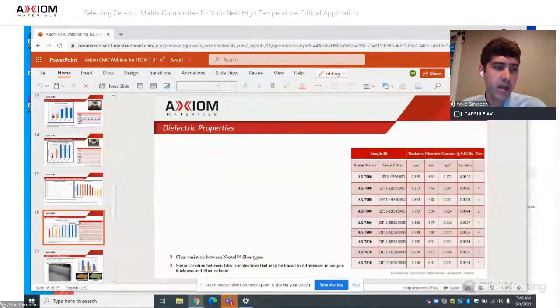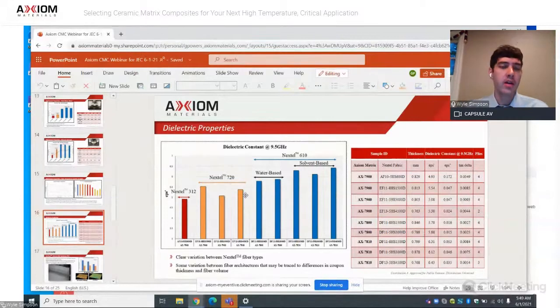Another interesting difference between the CMC components is the dielectric properties. The 312 fiber, which is the low-cost one, actually has a very low dielectric constant, and for that reason, it's typically used in radome applications, where you want to send a signal through without losing too much of it at high temperatures. So here's the difference: 610, the all alumina. Standard alumina has typically a dielectric constant around 10, whereas silica has it around 4. That's why you're seeing the difference in those dielectric constants, with the all alumina fiber having the highest and the more mullite fiber having the lowest, and the aluminum mullite somewhere in the middle here with the 720.